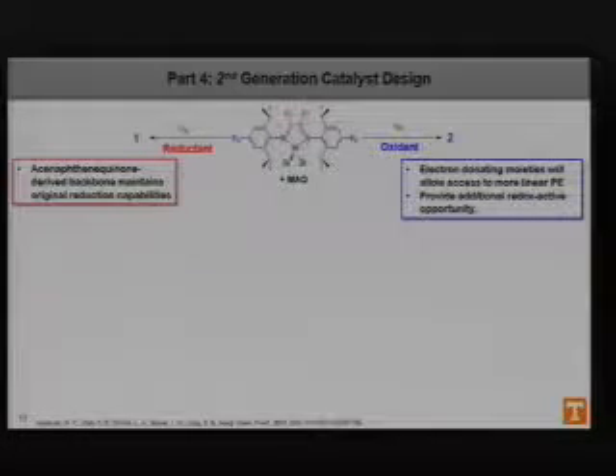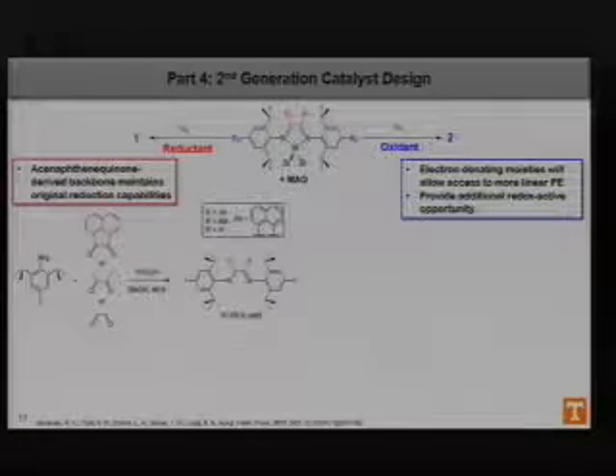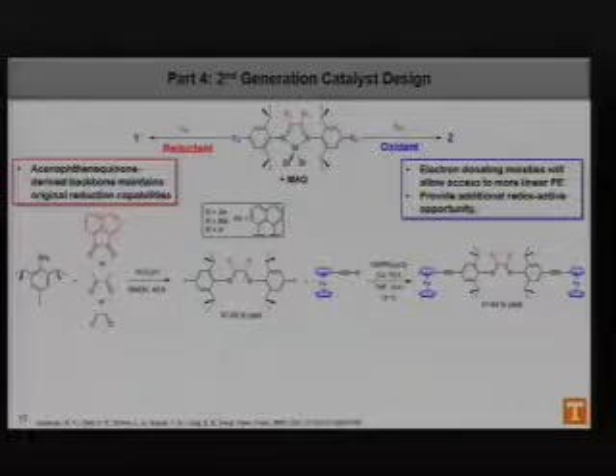These R2 groups could also provide an additional opportunity for another redox active site. So with this in mind, we set out to synthesize our own catalysts, and we chose to synthesize 3 based on the Brookhart catalyst that he had released in 1995, and they all used essentially just different backbones. And condensing this iodinated aniline onto each of these diones, we achieved this diimine here, followed by a double Sonogashira coupling to give the ferrocene modified ligand that I have shown here.